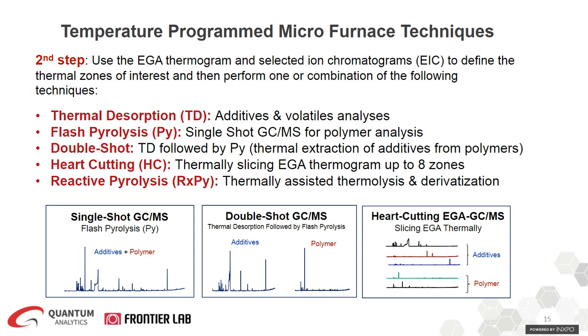But whenever you run, especially from your EGA, whenever you can see that your sample is a mixture of additives and polymers or copolymer, then you want to perform, of course, EGA first, but then a double shot might be used. Because in this case, you are separating and thermally extracting all those lighter and additive components from your heavier compounds in the sample. So you obtain 2 GCMS chromatograms. The first shot, as shown here, is the thermal desorption chromatogram that detects all those volatiles, lighter components, and additives. And then the second shot, where you set your furnace at a higher temperature, identifies the heavier and polymeric compounds.